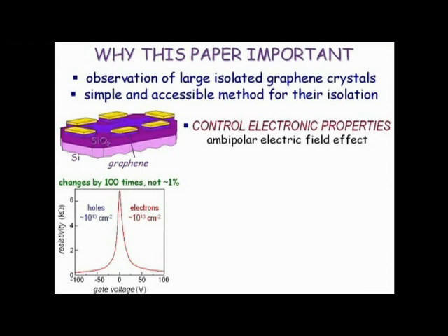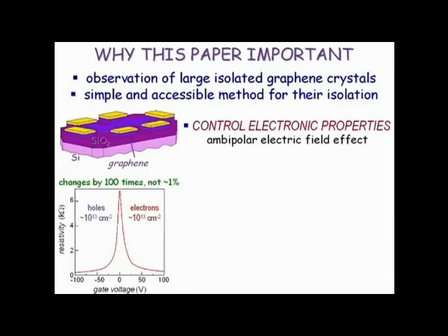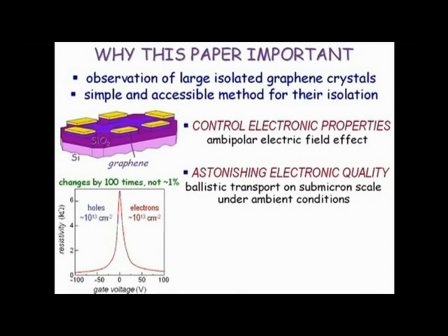What that essentially means is, if you evaporate a film of gold, it will stay a film of gold. Whatever you do, you can't really change the material. Here, by applying voltage to the substrate, we change it from a good metal with electrons as charge carriers to a good metal with positive charges as carriers, through a semiconducting state where resistance grows with decrease in temperature and so on. It's a huge change in properties and change in resistance, not by 1%, but by a factor of 100. Even more importantly, what no one could possibly predict, that the quality of the material would be high.